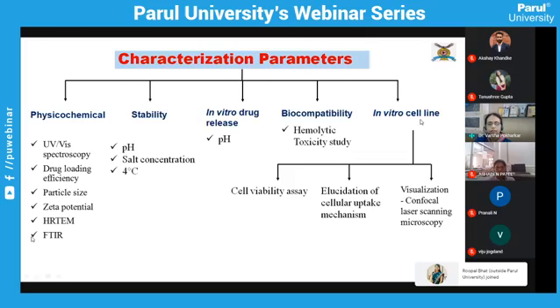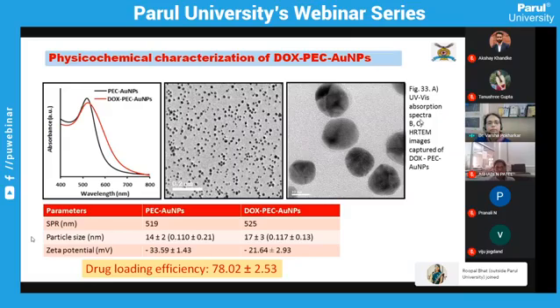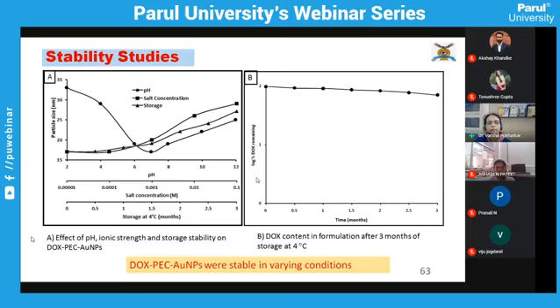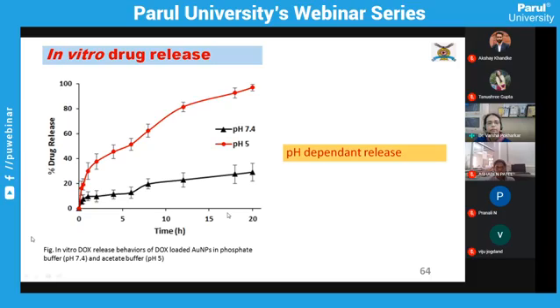Several characterization parameters we have undertaken. The drug loaded particles were further characterized for surface plasmon, HRTEM, and size. Stability studies were done. The stability of doxorubicin here was established for a period of 3 months at a storage condition of 4 degrees. For drug release, similar to the earlier case, we got a pH dependent release, which is of benefit here because once receptor mediated endocytosis occurs, the endosome has an acidic pH, and that is where the drug release is majorly going to occur. So a pH dependent release was observed.